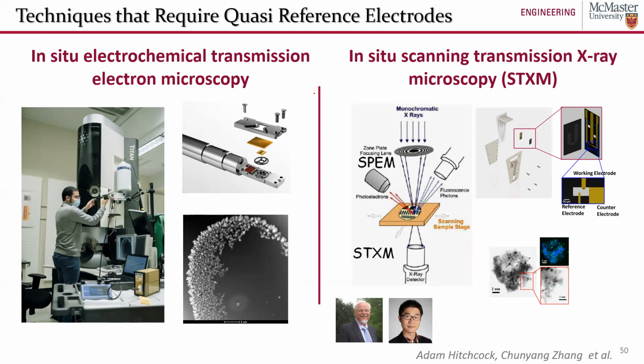Here are two areas of research that my group is actively working on, where we are commonly using quasi-reference electrodes in these microchip reactors. We're doing a lot of in situ electrochemical transmission electron microscopy. You can see Ahmed Abdallah, a PhD student in my group, putting his microchip reactor into a TEM. On the right, we're doing a technique called in situ scanning transmission X-ray microscopy. That's a mouthful, but essentially we're able to do microscopy on materials where each pixel in that microscopic image is actually a spectrum that can give us chemical information about our materials. We're collaborating very closely with Professor Adam Hitchcock, here at McMaster University in the Department of Chemistry and Chemical Biology, really a world leader in this STXM technique, and Chunyang Zhang, a PhD student in my group, who was co-supervised by myself and Professor Adam Hitchcock.